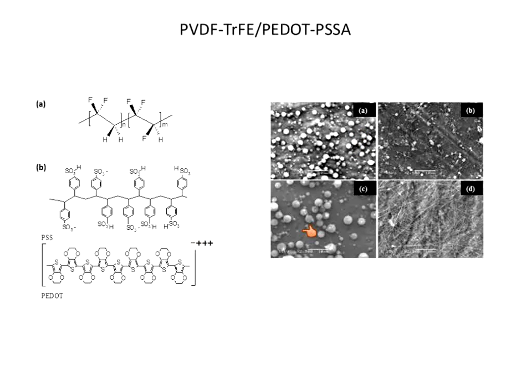You increase it to about 5 weight percent, and you begin to see indications of fibers being formed. So what we found is that if we really wanted to get fibers of this polymer, all we needed to do was add about one drop of PEDOT, and that makes the solution a little conducting. It reduces the surface tension of the solution. And right over here, we can begin to see the beginnings of fibers being formed as you electrospin PVDF with one drop of PEDOT in it. And certainly you can see in 5 weight percent.